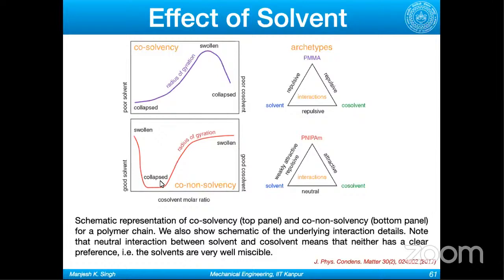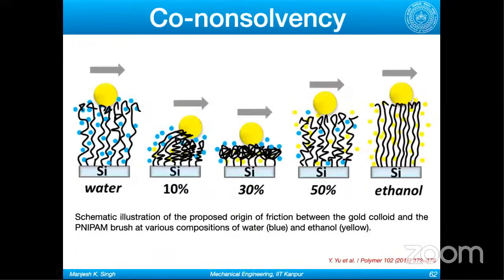The same thing goes for co-non-solvency. On both sides, the polymer brushes are in a swollen state, so they help in lubrication. But somewhere in between, they are in a collapsed state, so they don't form a brush-like structure, and you will have higher friction. And people have studied this, for example with a water-ethanol mixture.